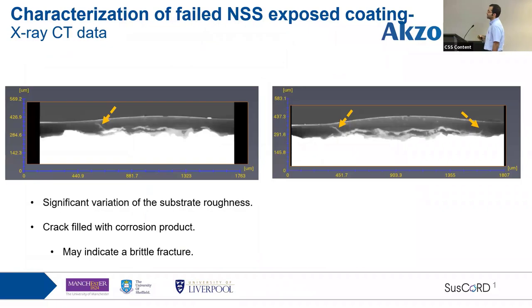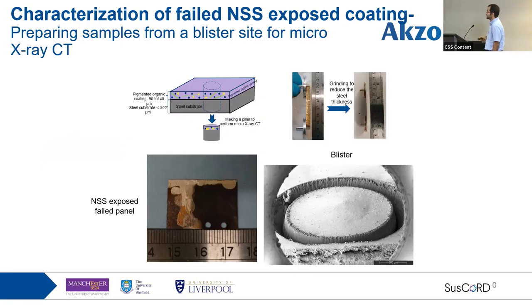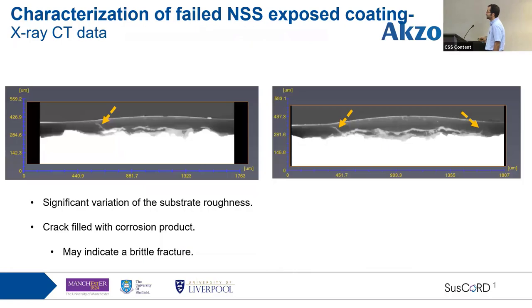So these are just two slices of the X-ray CT data from the entire blister. I think the slices are somewhere in the middle of this blister. And as you can see, we have crack formation, which are filled with corrosion products. But the other thing is that the data were relatively noisy, especially at the coating near the interface. That's because of the really rough surface of the substrate, which resulted in this noisy data. So I could not do segmentation and measure the pigment volume concentration and correlate that with my 2D segmentation data. But these data were revealing.